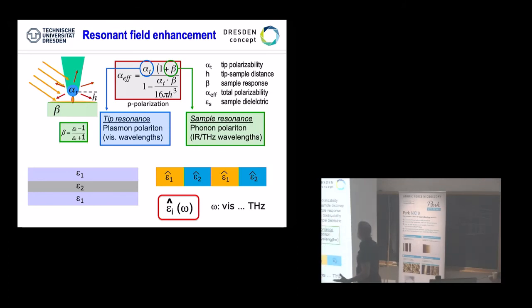That's a nice thing. There's more to say. There could be a resonance. We could say, okay, we take a tip, say silicon, whatever you want, or a nanoparticle at the tip, but there's a sample that has phonon or infrared resonances. It's barium titanate, for instance. We want to see soft modes, and hence we can tune either of those, the tip or the sample, exactly to that resonance frequency. So we're not bound to a frequency which is 2 or 3 kilohertz, but we can really change the whole frequency range in order to get this induced dipole interaction on that frequency that I want.